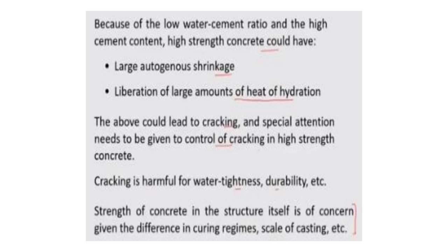And second is the liberation of large amounts of heat of hydration. It is because we all know cement hydration is an exothermic process. So more will be the cement content, more will be the exothermic reaction, and more is the exothermic reaction, greater will be the heat of hydration. The above could lead to cracking, and special attention needs to be given to control of cracking in high strength concrete. So these two mainly result in cracking.